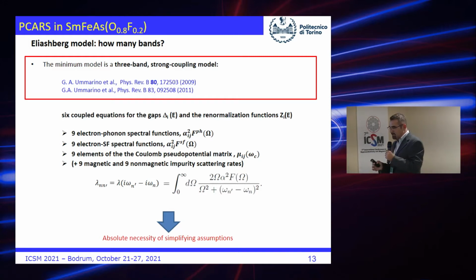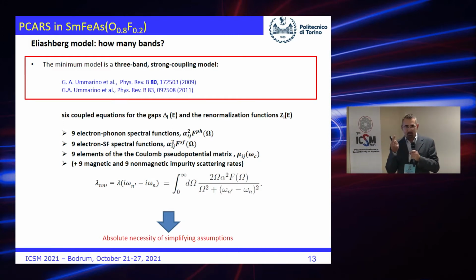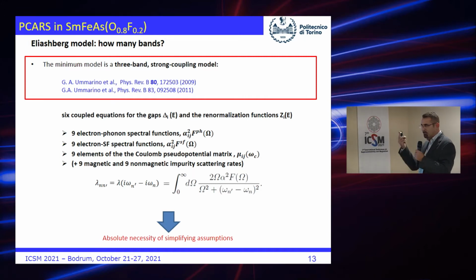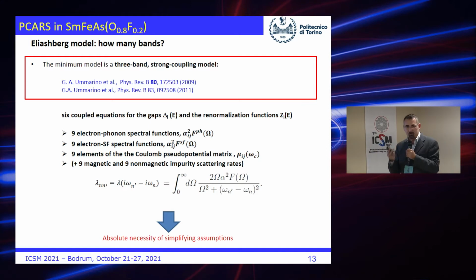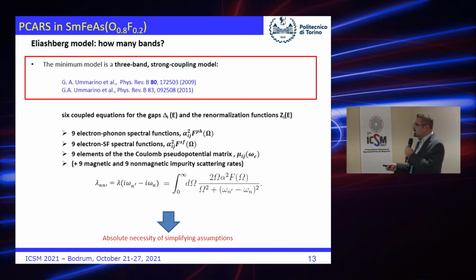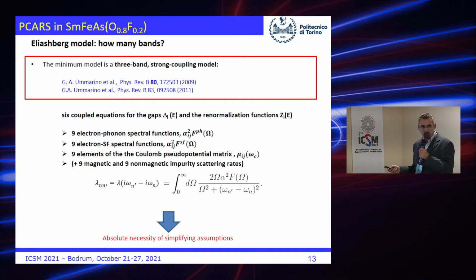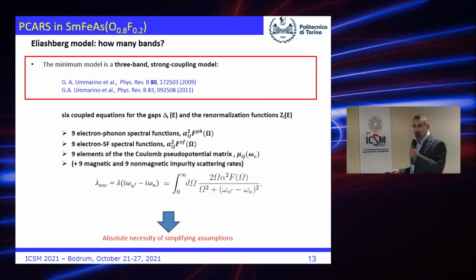So, the Eliashberg model. In principle, the Eliashberg model for one single band requires solving two coupled equations. One for the gap, which is a function of the energy, and one for the renormalization function. It can be shown, and I won't go too much into details, that for these iron-based superconductors the simplest model you must use is a 3-band model, but with strong coupling. Because if you use a 2-band model, it doesn't work. But 3 bands means 9 elements: in principle, we should need 9 electron-phonon spectral functions, because phonons are still present. We cannot neglect them in principle.